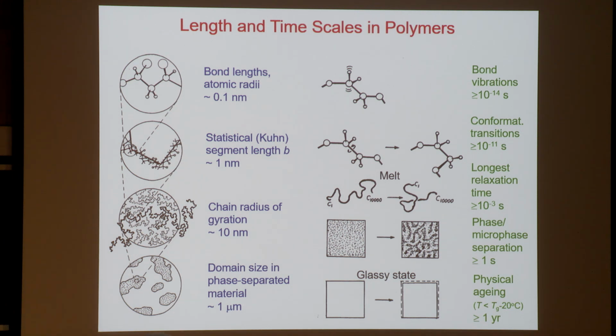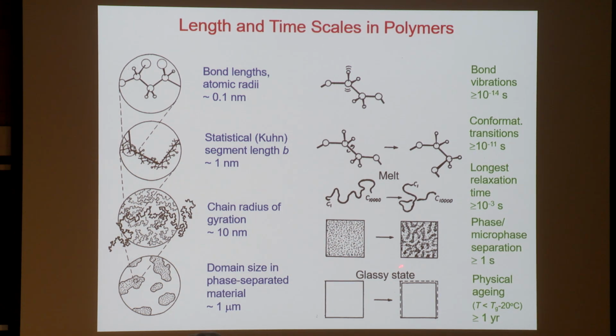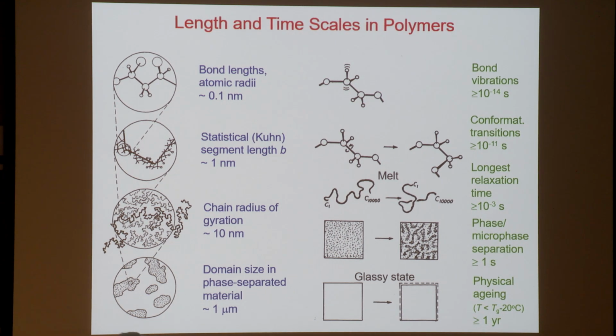If we have phase and microphase separation phenomena, these have characteristic times of seconds or longer. And when we go to the configurationally arrested glassy state, the very slow process of physical aging, whereby the properties of a polymer change with time, may have characteristic times of years, 20 degrees below the glass temperature. So from bond vibrations to physical aging, we have something like 21 orders of magnitude, and clearly one single modeling approach would not be sufficient to address all this.